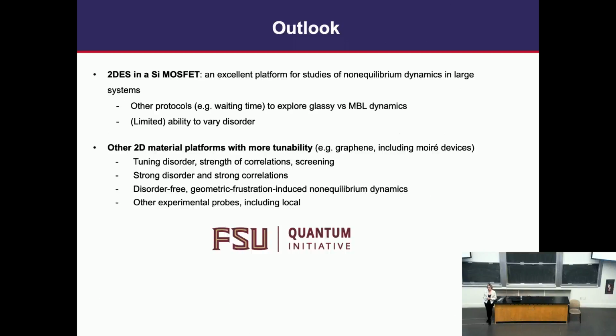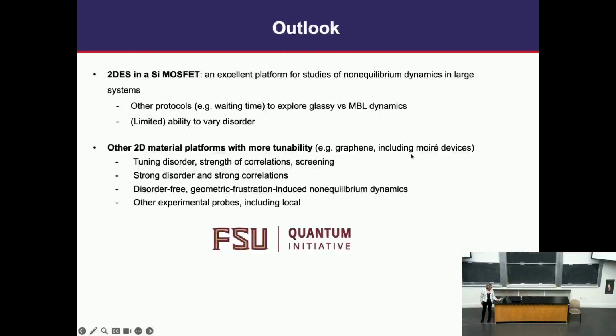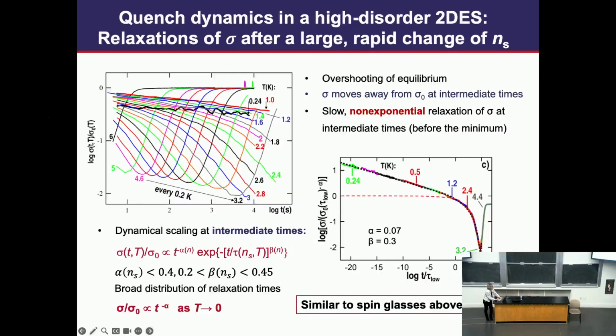Can you run - so you saw this stretched exponential relaxation. That's similar to spin glasses, but is the actual stretching parameter the same, like this beta term? I think they're very similar. And in our case, this stretch term actually vanishes in the zero temperature limit, but you can see they're small, it's 0.4, and it depends on density.